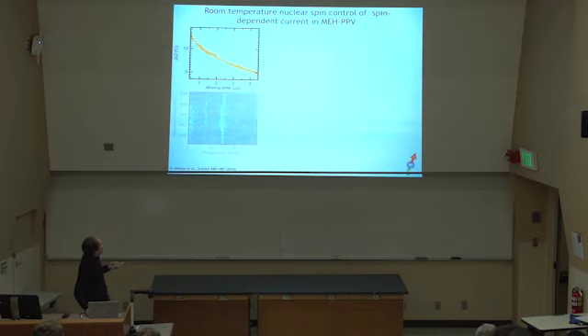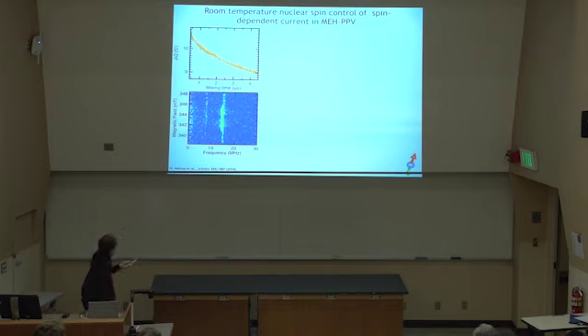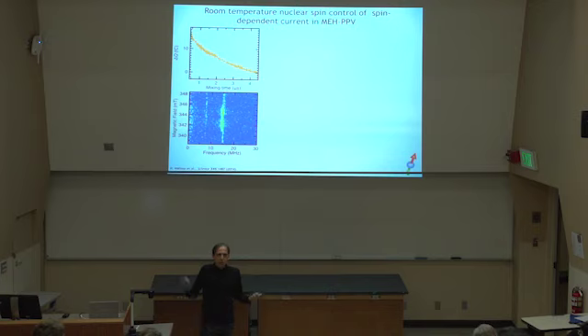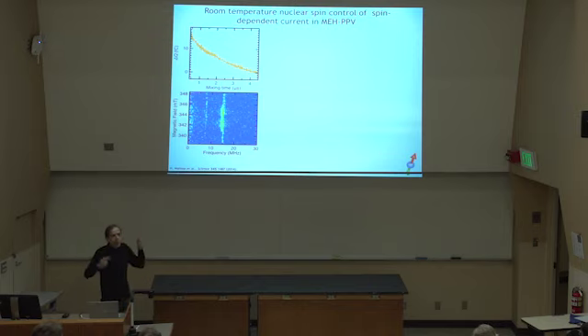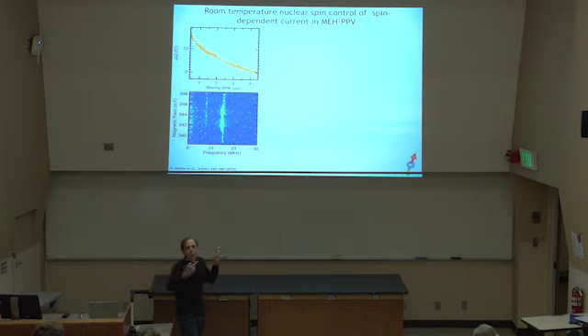And that it's not noise is what you realize immediately when you Fourier transform the wiggles. And what you get here is this frequency component. So this is magnetic field scale. Again, that's around the electron spin resonance frequency where this occurs. And you get something like 14.5 megahertz, which for the applied magnetic field here around 342 to 346 millitesla corresponds to the proton Larmor frequency. And so what these wiggles actually are is a modulation of your electron spin echo decay by nuclear spin motion of your protons. That's a pretty daring claim.